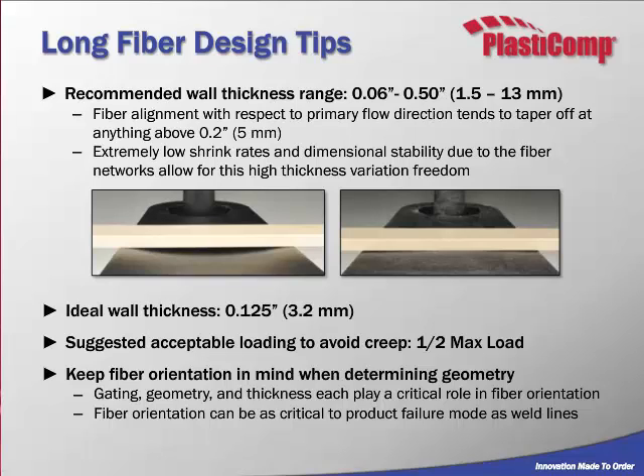So when people ask about creep, we say try to keep your loading under half the max load that you're going to deal with, just to reduce creep also. And then also keep in mind your fiber orientation, as I stated earlier. That's a big deal. If you're getting a lot of tumbling in your part because you made it too thick, you're going to have diminished strength in the part.